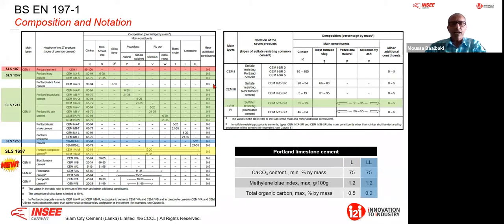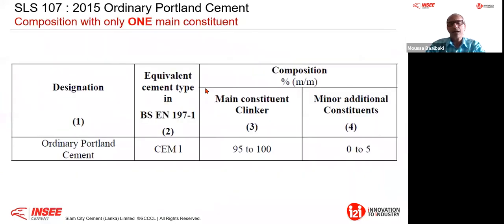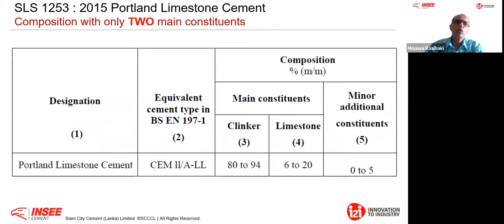Now, if I come to the composition, for example the OPC, the main constituent is only one, clinker. In OPC, we have clinker and what we call a minor addition, 0 to 5%. When we come to the SLS 1253, the Portland limestone cement, here you don't have one constituent but 2 main constituents: clinker and high-grade calcium carbonate, what we call limestone, the LL class. This is a high grade. Also, you have the minor addition constituent, 0 to 5%.